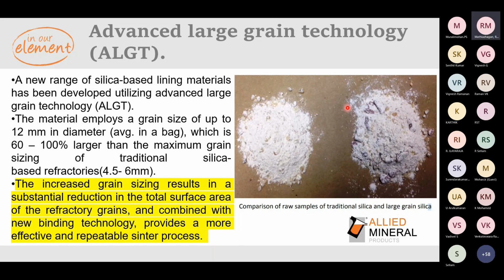Normal grain sizing is 4.5 mm to 6 mm, but this product contains 12 mm on average in a bag. There are certain grains which are a little bit bigger, but if you consider the average, it comes to about 12 mm particle size, which is about 60 to 100% larger than the maximum grain size of a traditional silica, which I said is 4.5 to 6 mm. What it does is, the increased grain sizing reduces the surface area exposed, and this is not only boron oxide; it is a special binding agent, so that the larger grains are kept on hold during the sintering process. This new binding agent with the grain sizing gives you a better sintering process and helps in attaining a better hot phase.